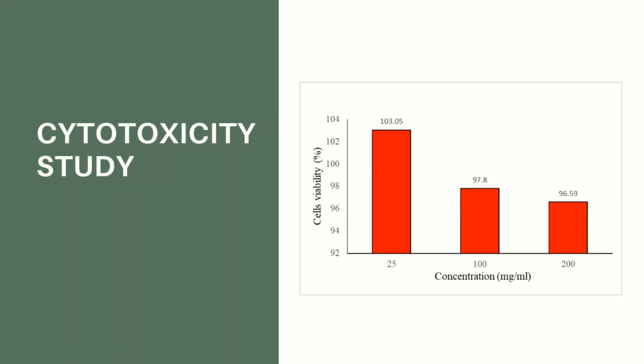In order to determine the biocompatibility of the collagen hydroxyapatite composite, an in vitro cytotoxicity test was conducted on the composite sample. Based on the standard protocol, when the cell viability obtained is above 80% after the analysis, the sample is considered a non-cytotoxic or biocompatible material.